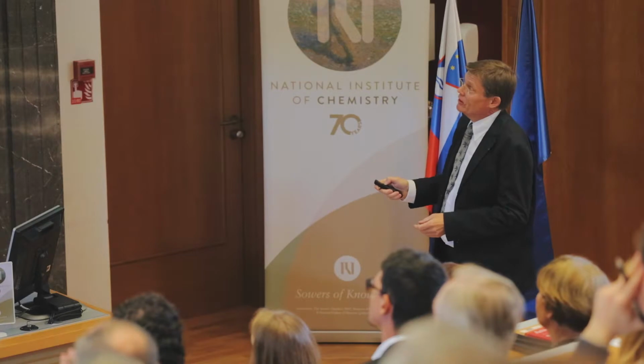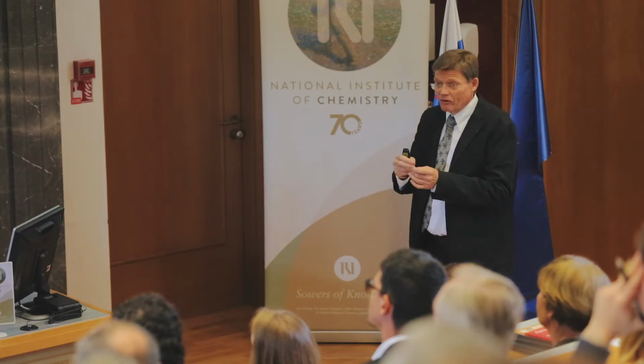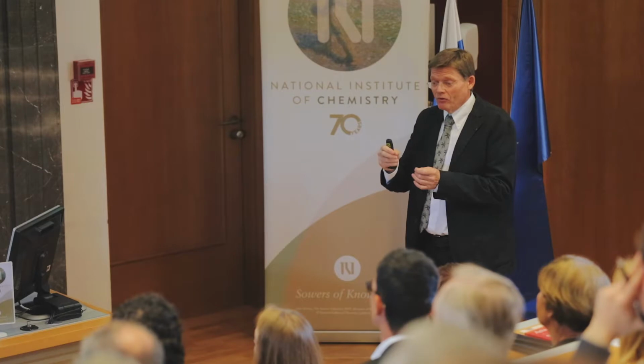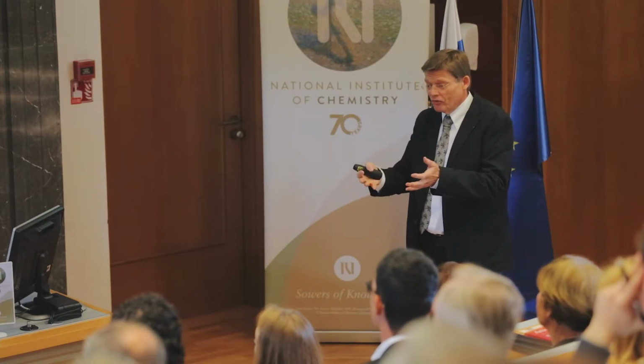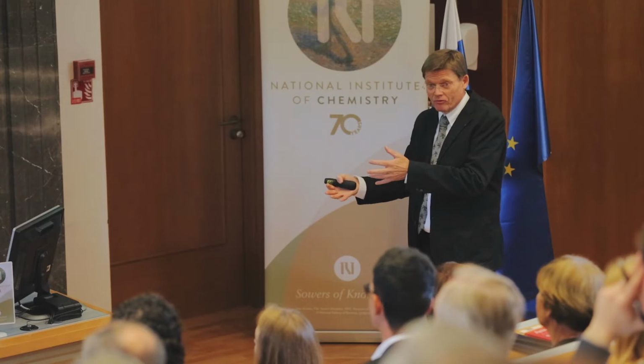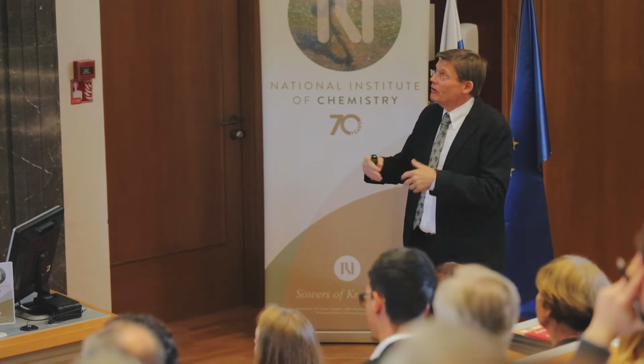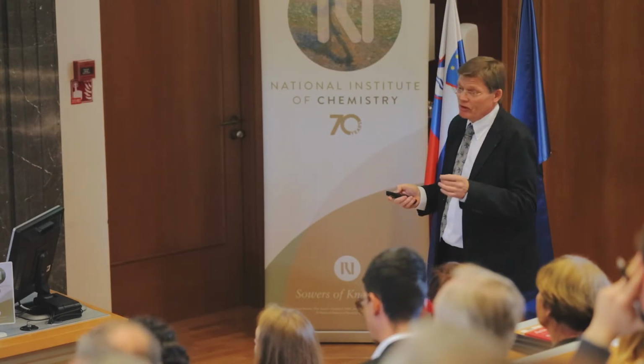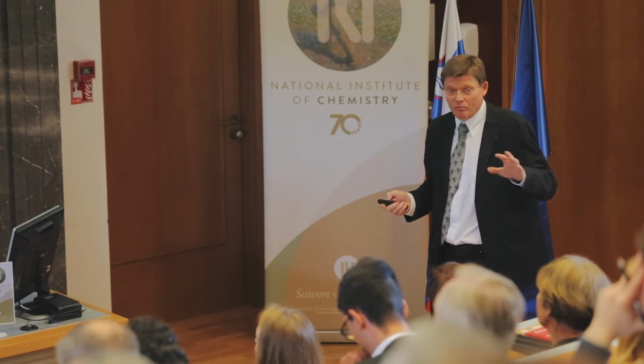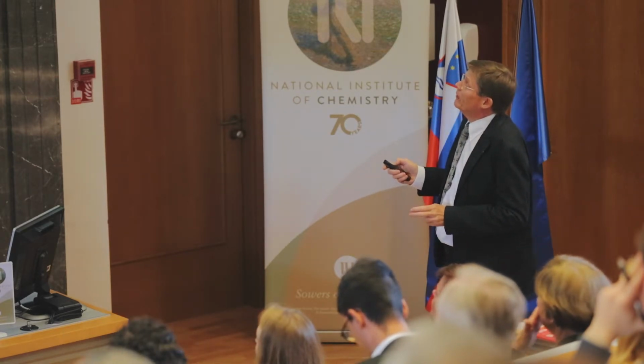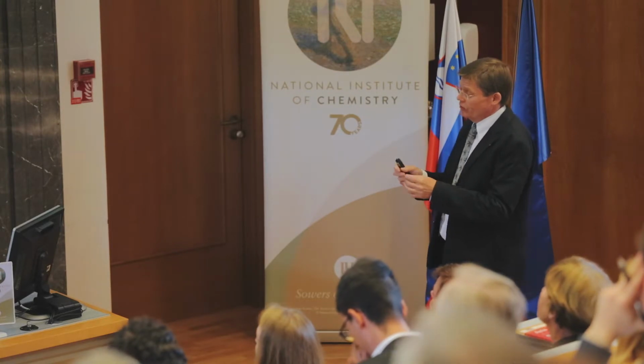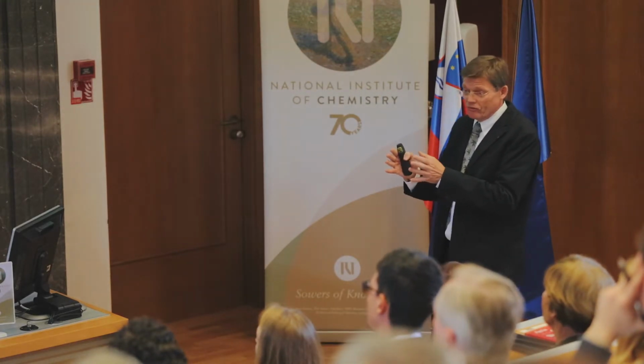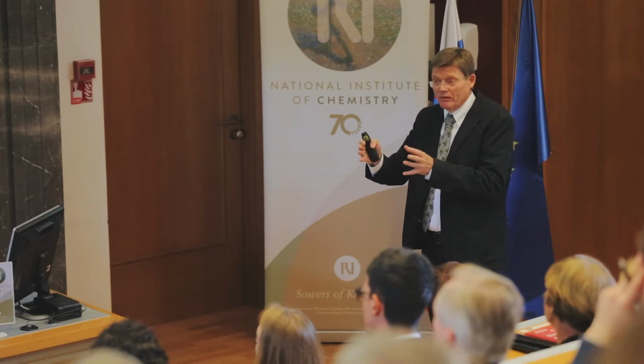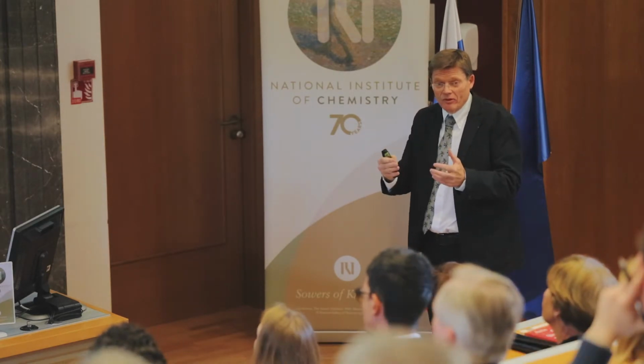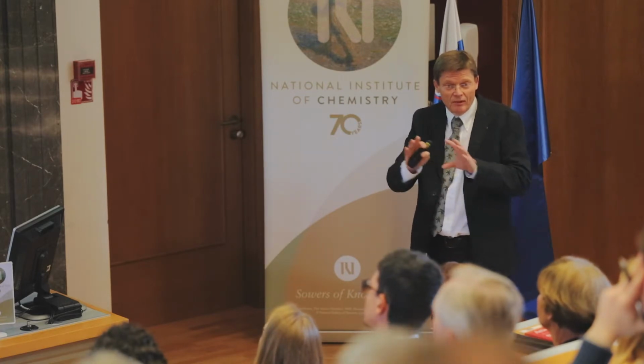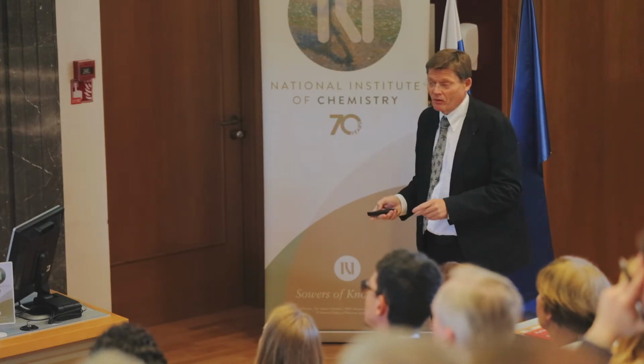So what about the resistor? It can be shown that this generalization is simple, because instead of just the voltage, we also have a chemical driving force. In formal terms, this can be done by generalizing the electrical potential to the so-called electrochemical potential. It's pretty simple. Capacitance is more difficult because what you normally have in a capacitor is a dielectric effect. You polarize your material inside. Now this chemical capacitance is something different because you store something. So they are separate. They cannot be so simply connected.